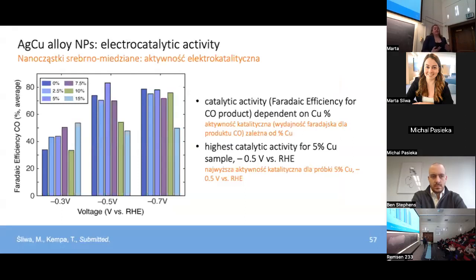We investigated the catalytic activity of these systems by measuring the Faraday efficiency for the products that they form in the CO2 reduction reaction across this compositional range, so from 0 to 15% at 3 overpotentials or applied voltages. For those who aren't familiar, the Faraday efficiency is a measure of the efficiency of a given electrochemical transformation in a process. It's a ratio of the electrons that go into the system versus how many electrons are actually used to make a specific product.